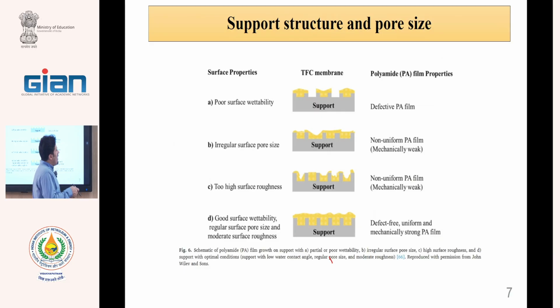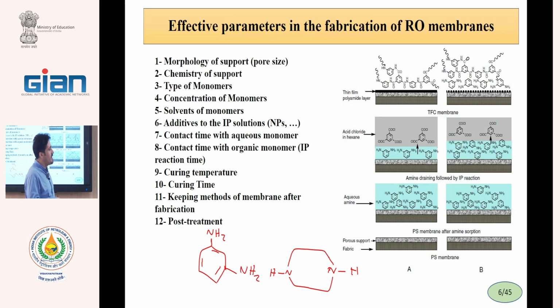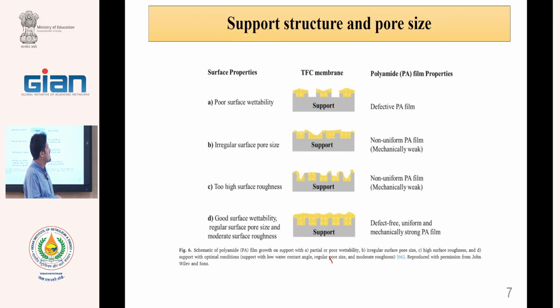Okay. The second one, the pore size distribution. When we have a big pore, the big pore will have a bad layer and cause non-uniformity. This is good, but this is bad, and these bad pores will reduce the rejection. Okay, we must have a good coating with uniform thickness. But when we have this bad film, therefore we have bad rejection. Therefore, we must control all of these conditions, and there are many examples that I can speak about the effect of all of these parameters, but because we do not have time, I only speak about the support structure.